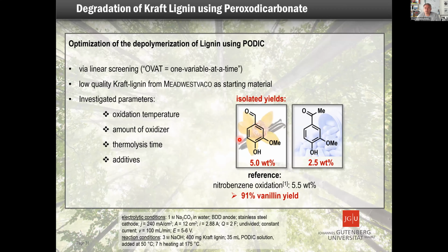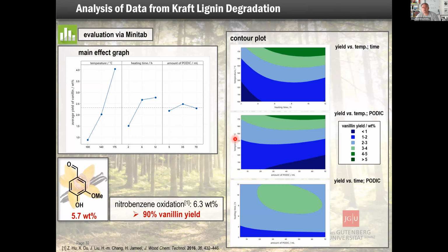If you look at that, you get directly 5% vanillin and a significant amount of the acetovanillone, which was a little bit lower before. If you compare this to the nitrobenzene oxidation, we are once more much higher. We are close to over 90% of the reference oxidation. And that means here at that point we are really on a good way. And the important thing is the nitrobenzene oxidation is also a kind of makeup. This PODIC is a makeup chemical for the system. You take out the vanillin and the rest goes back to the plant.